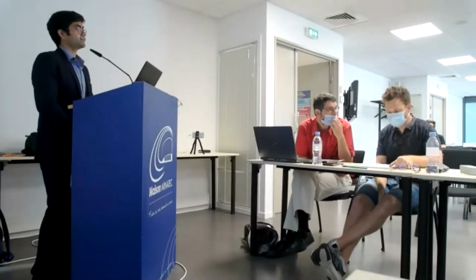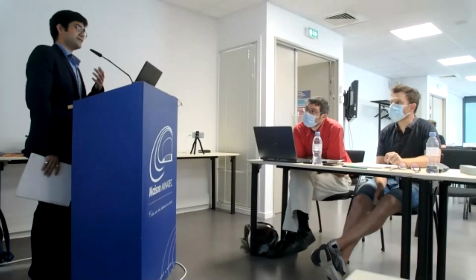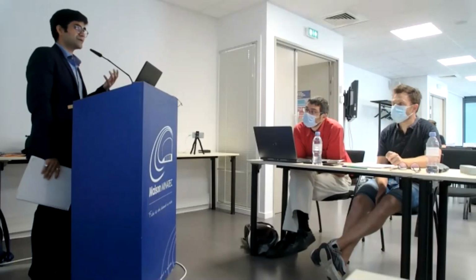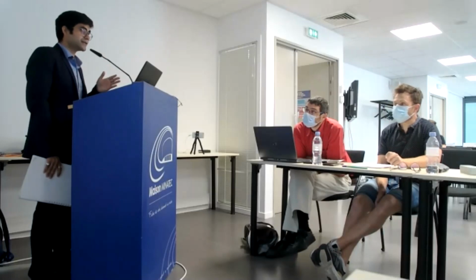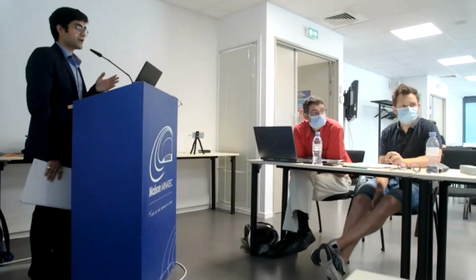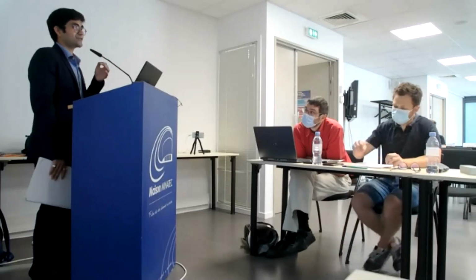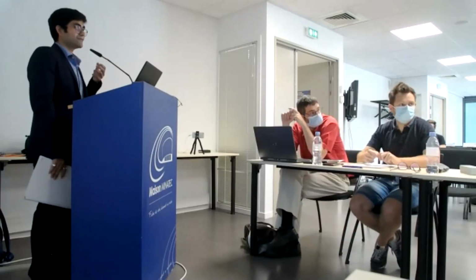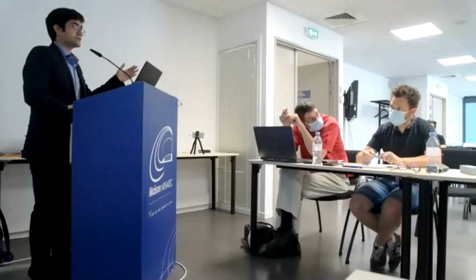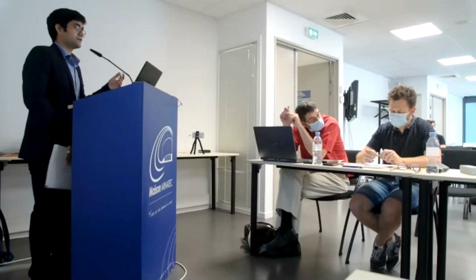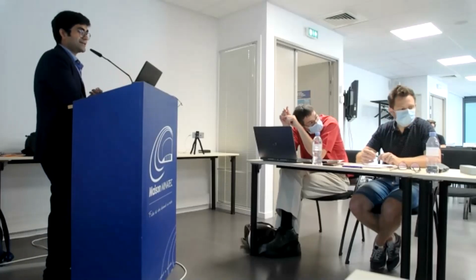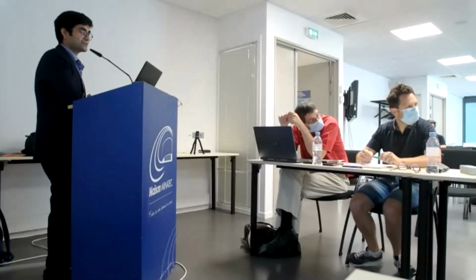Yeah, clearly, previously, way before the RDG model came into existence, people thought that it was the strain which affects the cracks to initiate. But then there were other models which clearly stated that it's not the strain, it's the strain rate, the rate at which strain is occurring, which plays a key role in the cracking initiation. So if I understood your question well, your comment is that if we change the process, will the effect of strain rate affect the cracking tendency to a great extent? I have no idea, but I was thinking that if you have a slow solidification condition, you may have some strain relaxation in the solid that will put less strain rate on the liquid films.